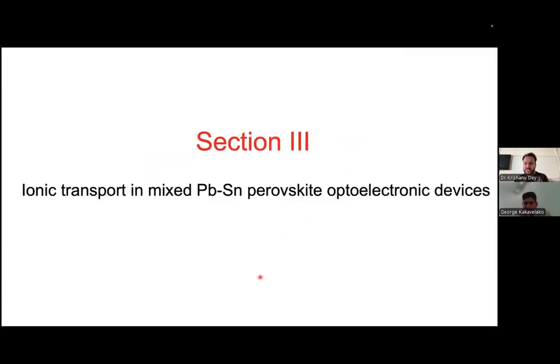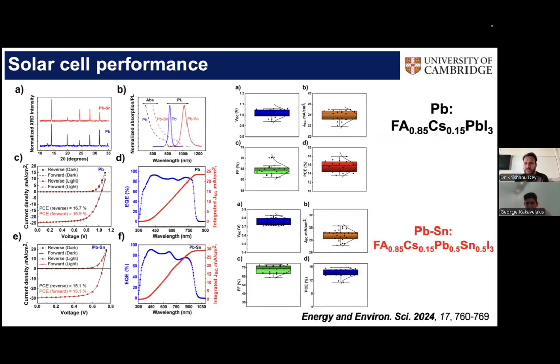Next, we wanted to see whether this kind of behavior is specific to field effect transistors, or can we generalize it? So we do similar kinds of measurements now on an optoelectronic device, a vertical structure device like solar cells. So we make some solar cells with a very similar composition, pure lead versus lead-tin. Let's say we make some PIN solar cells with these compositions. I deliberately did not put any kind of passivation in these materials because we wanted to specifically look at the effect of tin. So we can obtain 15 to 16% without any passivation, which was decent at the time.